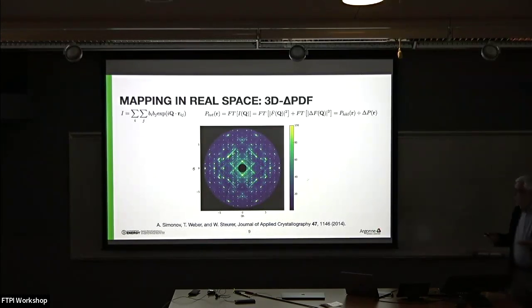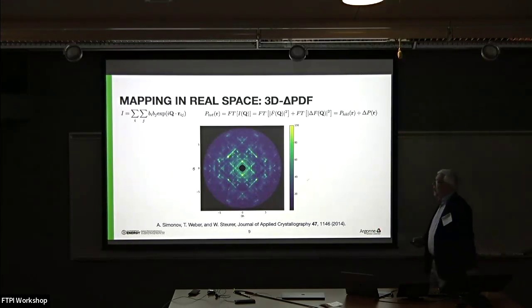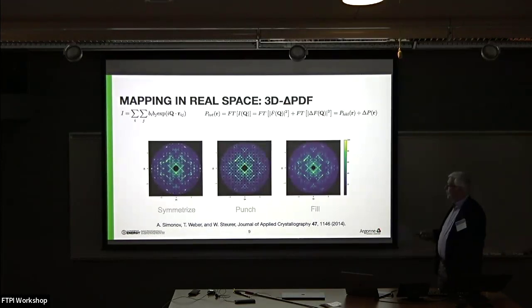And what a group at Zurich realized, Thomas Weber and colleagues at ETH Zurich, was that if you could separate the scattering into a component from the average structure and components that represent deviations from the average structure, if you Fourier transform that, it remains separated. So can we do that separation? Well, of course, it's quite trivial because we know exactly where the average structure is encoded. It's encoded in all the Bragg peaks. So we just get rid of all the Bragg peaks. Now that would generate Fourier ripples, so you paper over the cracks. And now we have essentially just this quantity here, which we then Fourier transform. This whole process is called punch and fill.